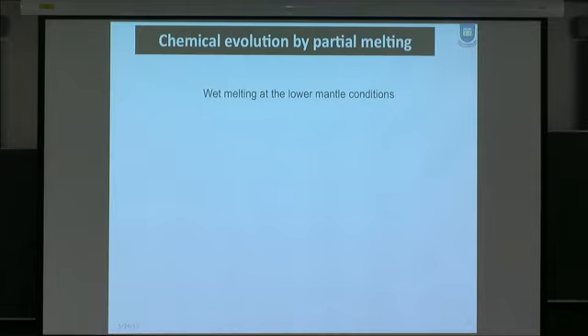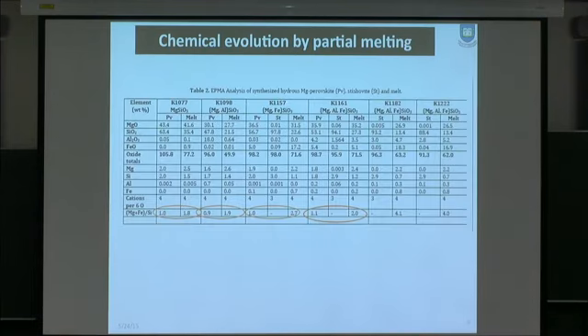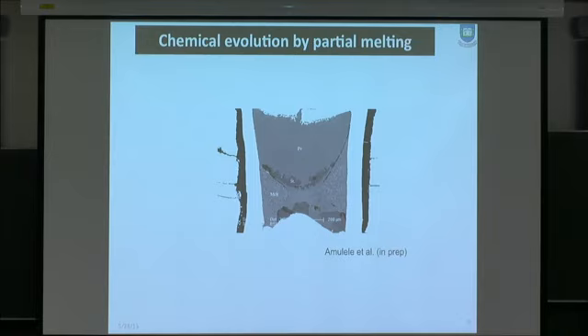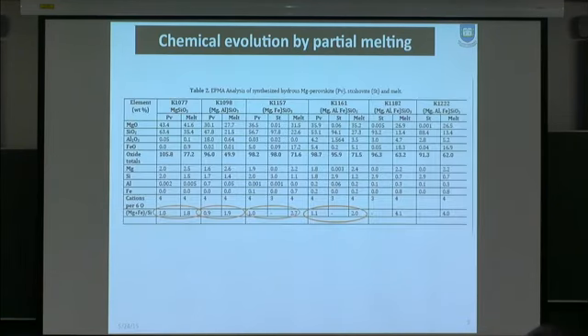As I mentioned to you earlier, partial melting is a very important process to control the chemical evolution. And the way in which chemical evolution occurs is controlled by the chemistry of melt and solid. When you do melting experiments like this at lower mantle conditions, we started from perovskite, bridgmanite materials with some water, and at the end of the experiments, we found that a large fraction of materials goes to melt, coexisting with some solid material. This one is the bridgmanite and stishovite. And then we determined the chemistry of the solid part and liquid part to understand what kind of chemical segregations are caused by deep mantle melting.